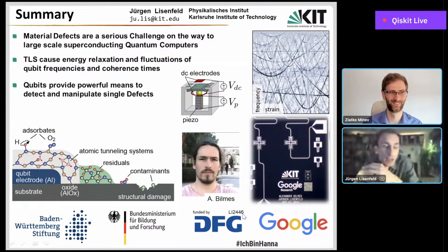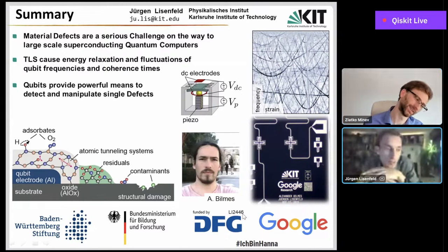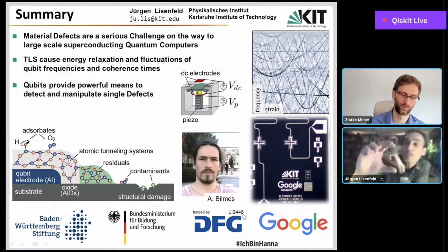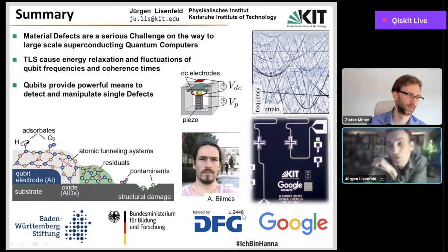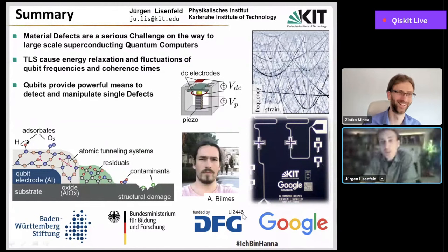And the effective strain change that we then generate in this material is of the order of 10 to the minus 7. So in fact, I can tell you that the 2 nanometer wide tunnel barrier is compressed by 10 to the minus 15 meters at the typical voltages we apply. So by a fraction of the size of a nucleus. So you would not see much movement there in this material, actually.